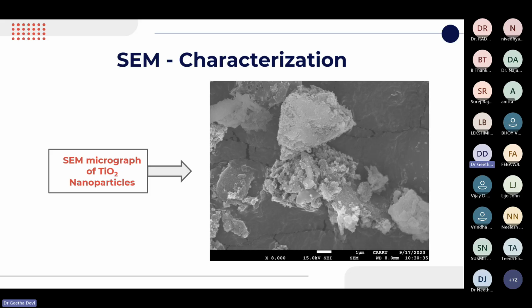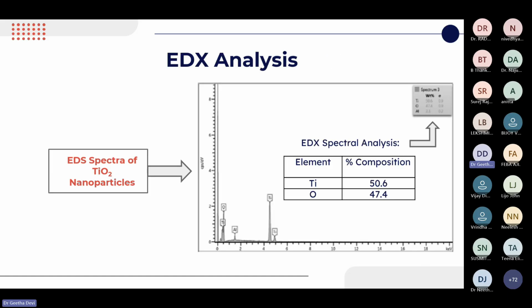This is the scanning electron microscopy image of the nanoparticles at a magnification of 8,000, and it is seen that the nanoparticles are formed, but in a clustered form, that is, a very thick distribution. And the energy dispersive X-ray analysis shows titanium is 50.6% and 47.4% oxygen. That shows the high purity of the nanoparticles.